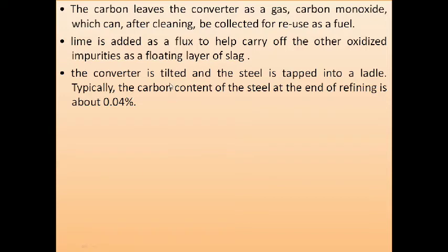The converter is tilted and the steel is tapped into a ladle. Typically, the carbon content of the steel at the end of refining is about 0.04%. So the carbon content at the end of the refining of the steel is 0.04%. In this way, we produce steel by using the oxygen process, that is, the basic oxygen steel making process.